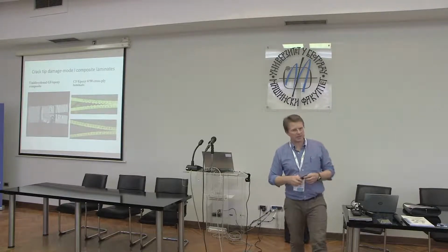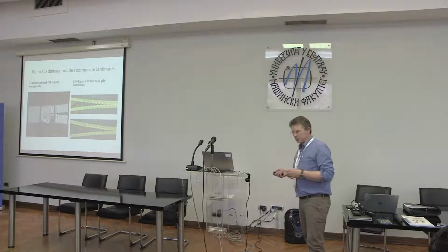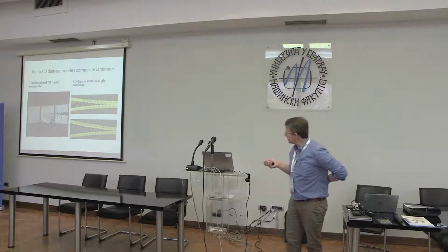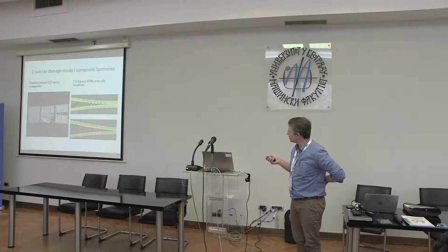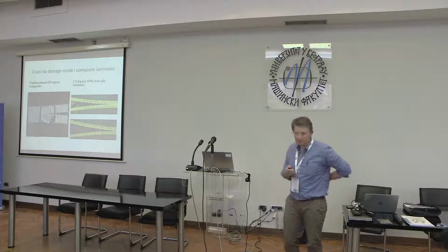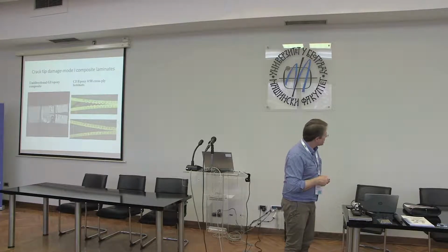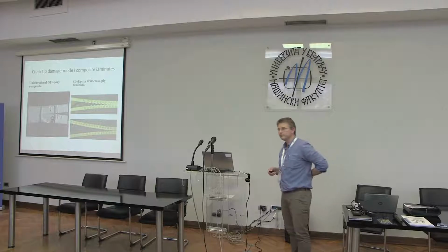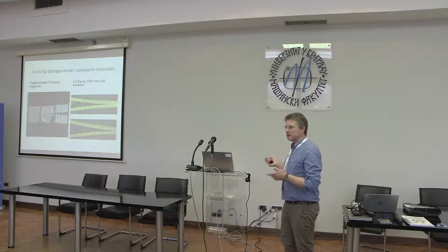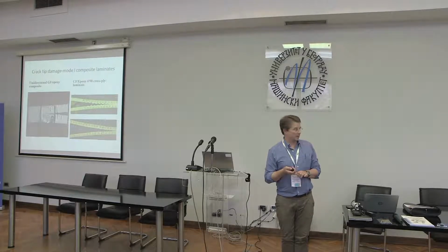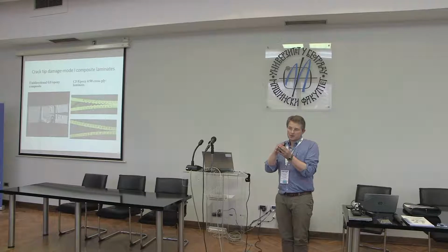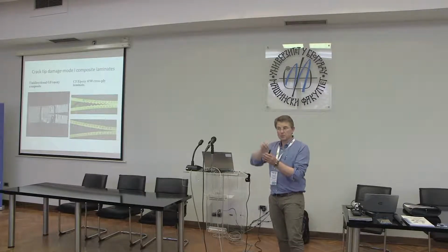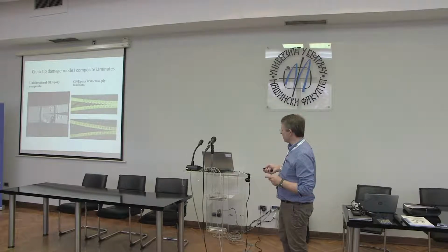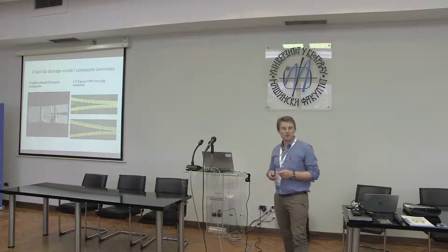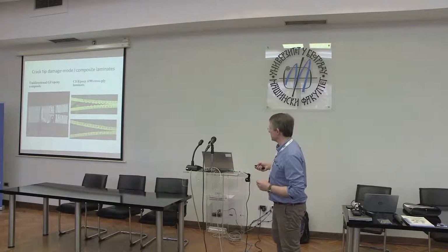There are other problems that can occur with these experiments, which we run into periodically. You can see in this case, this is a unidirectional glass fibre epoxy composite. So you can see here the initial crack. What's happened in this case is that we're getting extra cracks occurring in the composite arms. What this would lead to, of course, is extensive fibre bridging in the specimen. So the crack is sometimes bifurcating, or you're getting micro cracking of the composite above and below the main crack. Okay, so the validity of LEFM is getting significantly more strained in these sorts of situations.